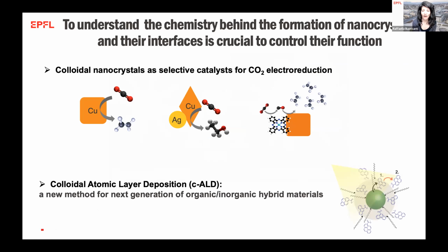So I wanted just to give you an idea of how understanding the chemistry of nanocrystals and of the interface, how interfacing these nanocrystals with different materials, can allow us to solve challenges in catalysis. So I showed you how the form and the shape of these copper particles determines their selectivity for CO2 reduction. So for example, these copper cubes of certain sizes become highly active for ethylene, or when we create interfaces of copper octahedra with silver, they can become selective for ethanol. We can also specifically interface these particles with molecular catalysts, and I didn't go into much detail about the mechanism because I wanted to keep the talk a bit light.